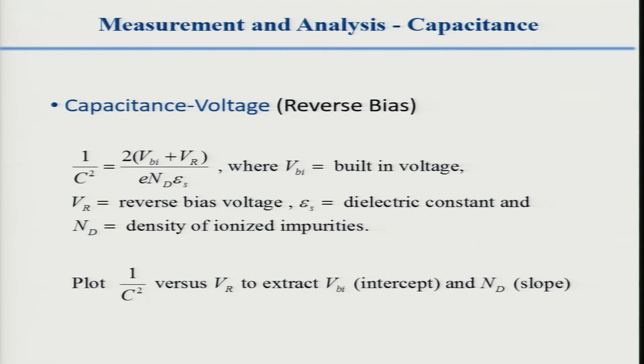It's also important to understand that we can do capacitance measurements in reverse bias. And so this is a well-known relationship which is solved by just showing that the density of ionized impurities is just constant in this depletion width. And you solve Poisson's equation, you get a shape for that curvature in the band, and you can derive using Poisson's equation that 1 over the capacitance squared goes proportional to the reverse bias voltage, and it has an intercept at the built-in potential.